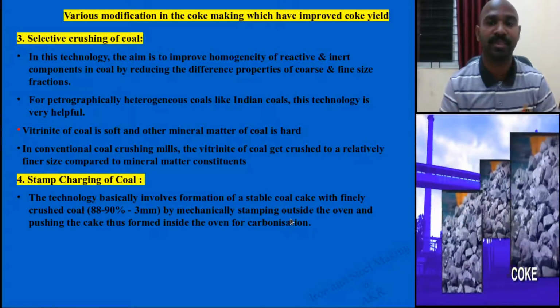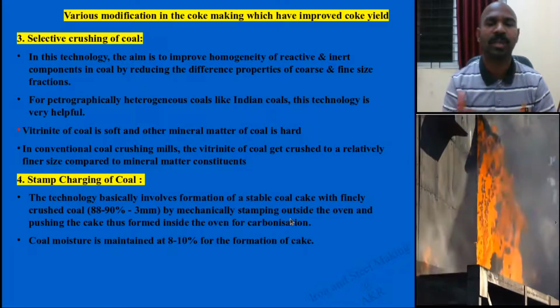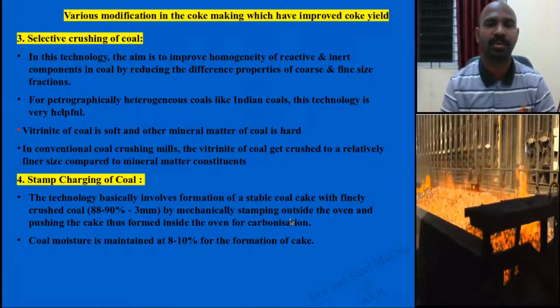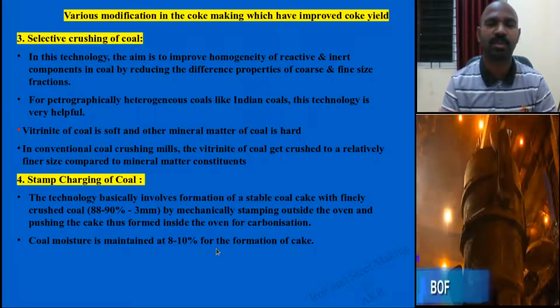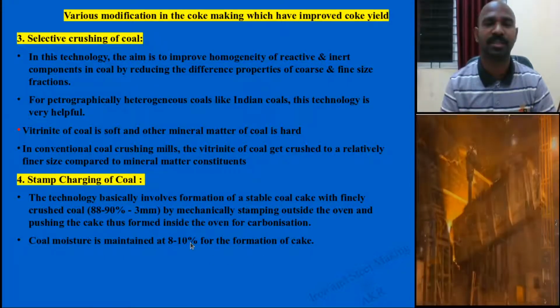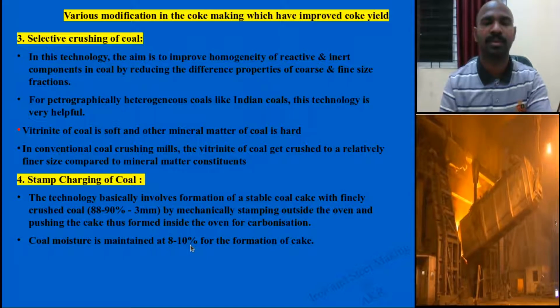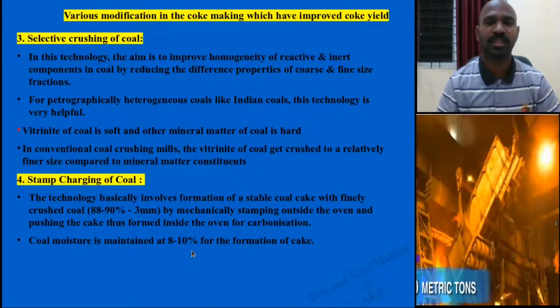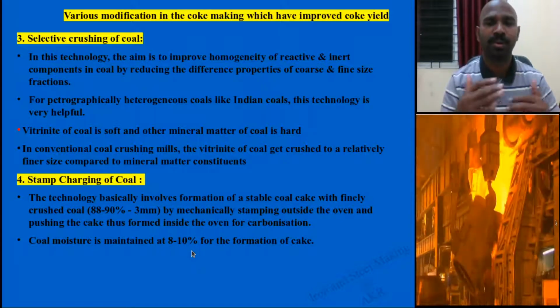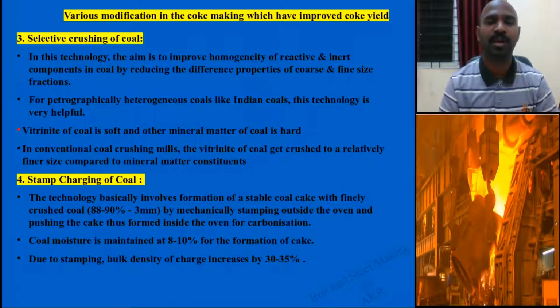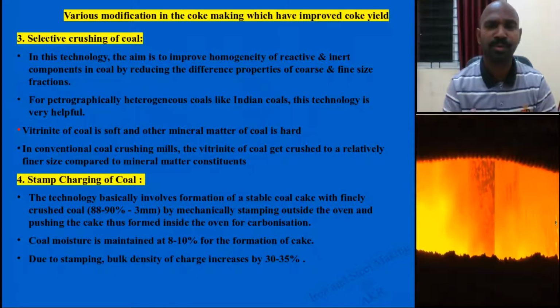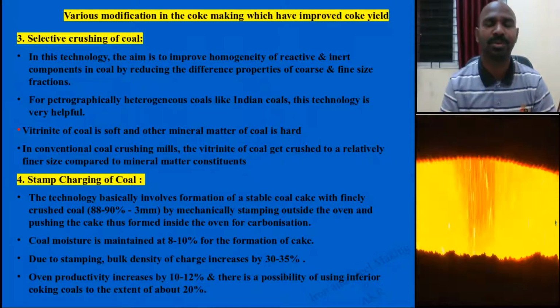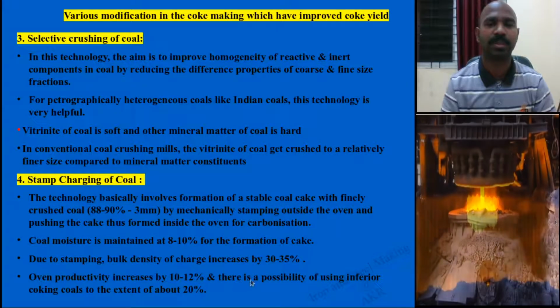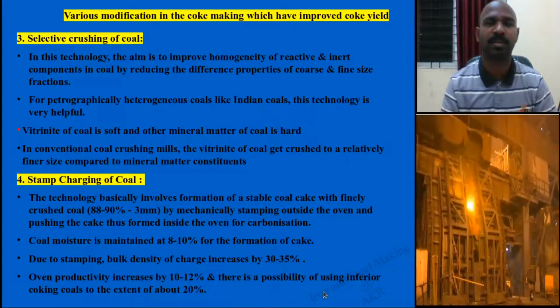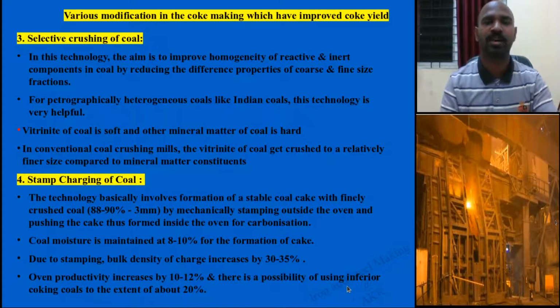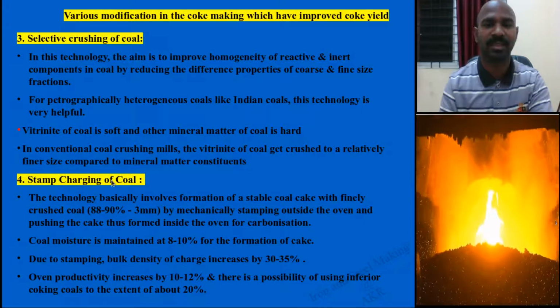Carbonization will be around 1100 degrees Celsius temperature, and the coal moisture allowed is 8 to 10% to form the cake. This much moisture content is allowed. This is the limitation of moisture or binder for the coal which you are selecting to make coke. And this stamping will give the advantage of increasing the bulk density, and overall productivity also increases by 10 to 12%.